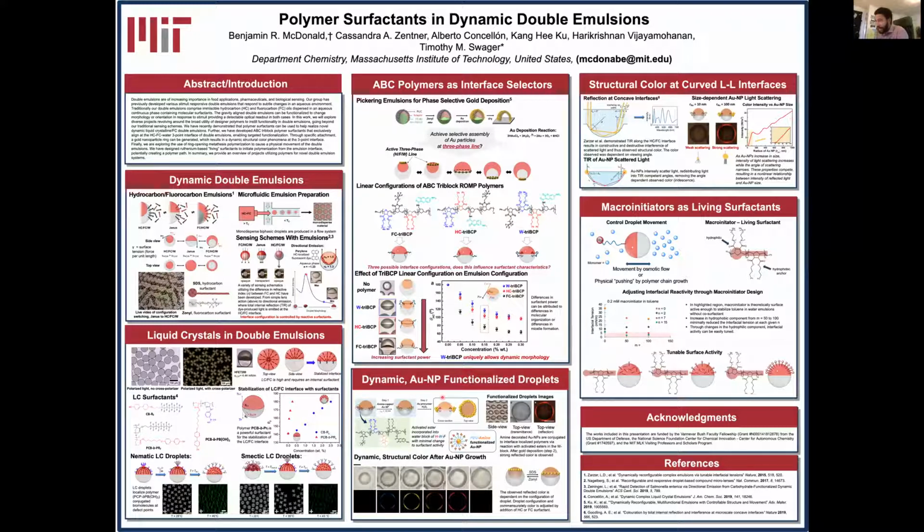And we added in this reactive ester group, which does not react with water, but reacts very quickly with amines. This is typically a choice for bioconjugation. We used it with these PEG-amine functionalized gold particles, so we have these amines on the surface that will conjugate our gold to the surface of the droplet.